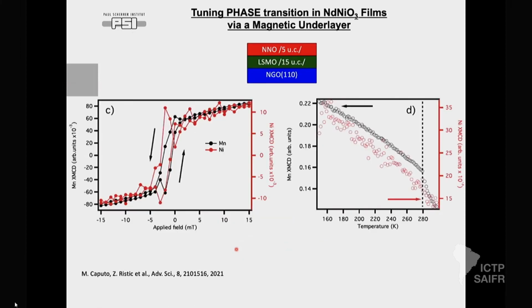For studying magnetism there are several methods, for example SQUID. But SQUID is problematic because it probes everything, the substrate, the buffer layer, and probing the film is not easy. For such a very sensitive system, we also use a synchrotron-based technique, which is XMCD. Our XMCD shows that manganese shows a ferromagnetic loop, but nickel also shows an XMCD signal, of course much smaller, on the order of 10 to the minus 3. So there is a ferromagnetic signature in nickel.